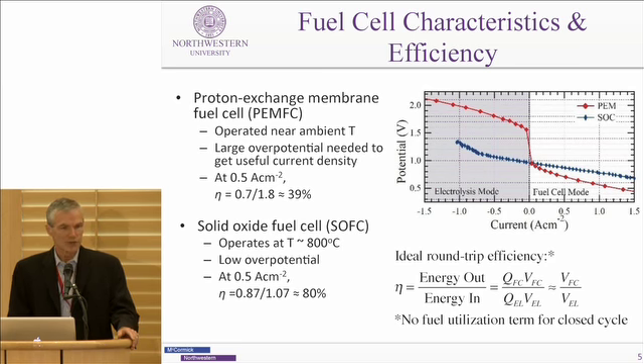The blue curve here shows the solid oxide fuel cell because it's a higher operating temperature, around 800 degrees centigrade or so, has lower overpotentials. You can see that there's a smooth curve here with very little overpotential. If you go through the same exercise and figure out the voltage here at 0.5 A/cm² in both modes, you're at about 0.87 divided by 1.07. That gives you about 80%, at least for an ideal efficiency. Okay, so there's some hope there.